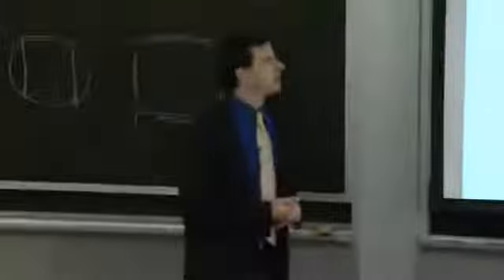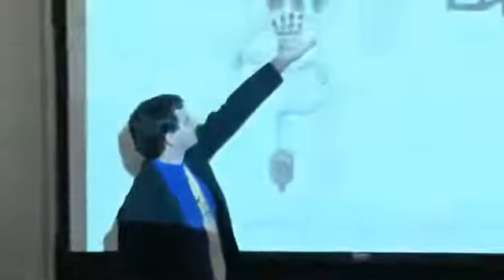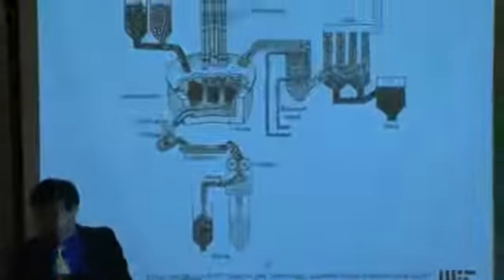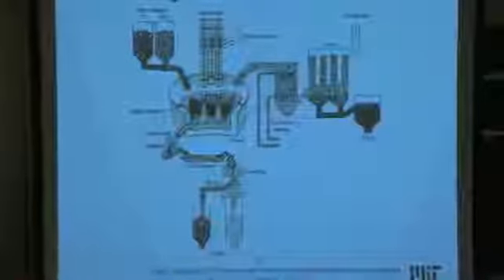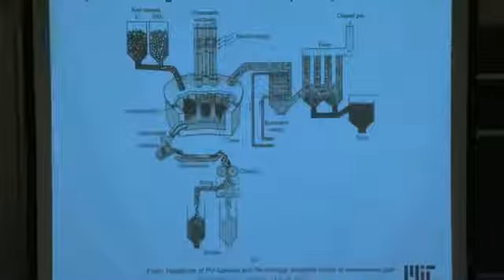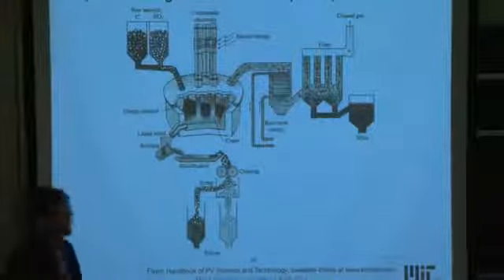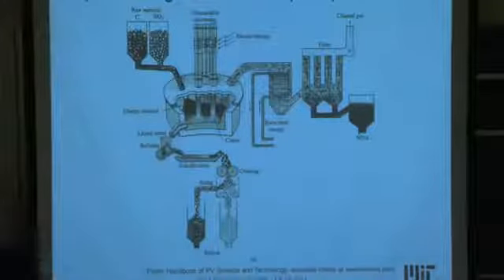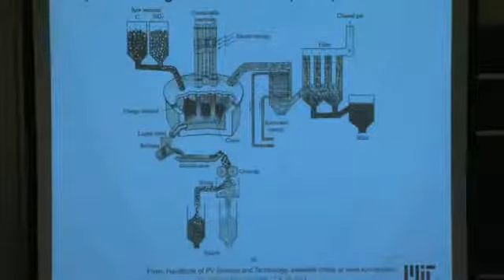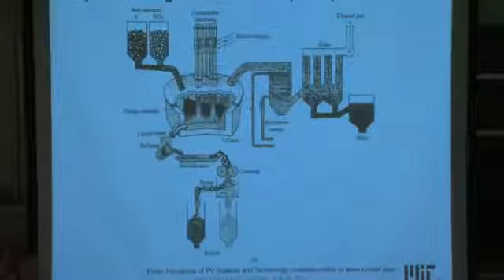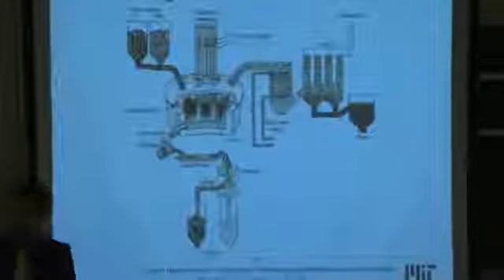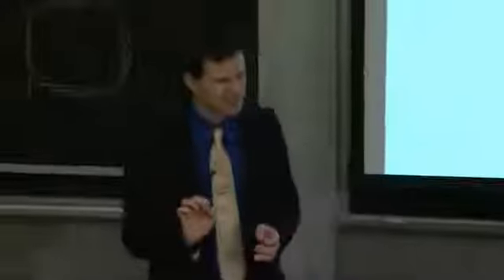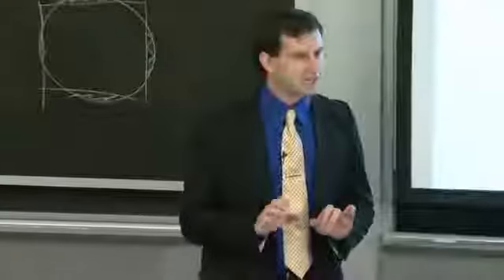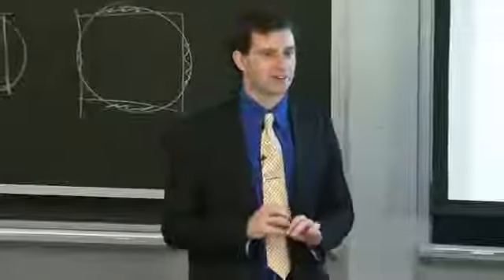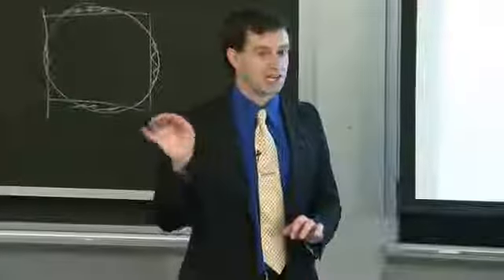Other byproducts coming out of this reaction include, this is liquid silicon up here. It's very high temperature, and there are gases and a lot of oxygen because of the reduction process. And so silica, or SiO gas, can be produced. And silica gas can begin aggregating and forming very small particles, almost like shards of silicon oxide material. And these can be on the order of 1 to 5 microns, and very rough and jaggedy around the edges.